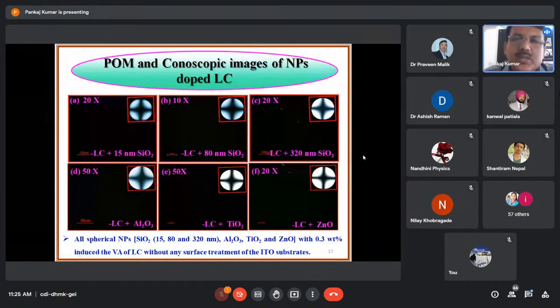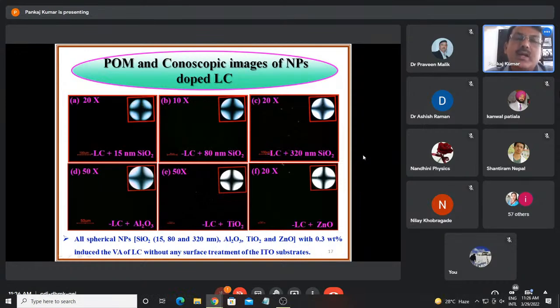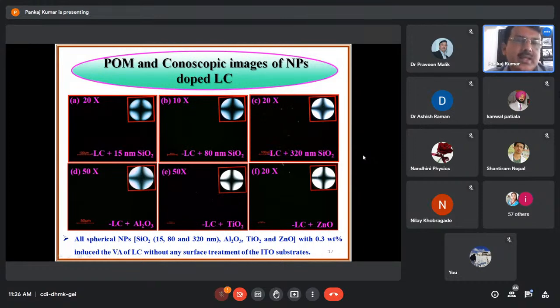So POM and conoscopic images of nanoparticle doped LC. You can see here negative LC plus 15 nanometer silica nanoparticles. Then figure B, at 10x, liquid crystal plus 80 nanometer silica nanoparticles. And figure C, liquid crystal plus 320 nanometer silica nanoparticles. These nanoparticles of size 15, 80 and 320 all give a very good dark state. These textures were taken under crossed polarizers, and in crossed polarizers, if the vertical alignment is there, then the initial state should be the dark state. You can see a very good dark state with 15, 80 and 320 nanometers.